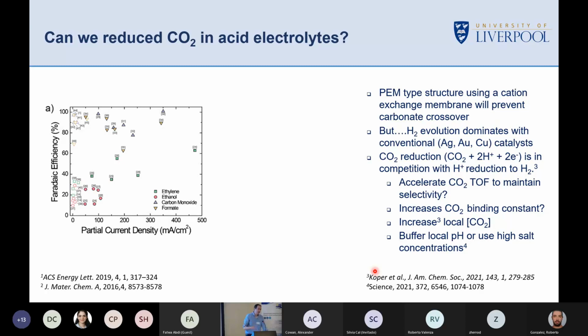If you take a silver electrode and put it into an acid-based system, and then you increase the current density, you'll see the Faradaic efficiency start to improve towards CO production. And that is one possible pathway. But even at 100 milliamps per square centimetre, this is data we took in the lab the other day, here's my CO Faradaic efficiency for a nice silver electrode, a benchmark one. The same electrode in the basic system was giving us about 80 to 90% Faradaic efficiency. We're getting very low here, and we can compare that to where we'd be working in the higher pHs.